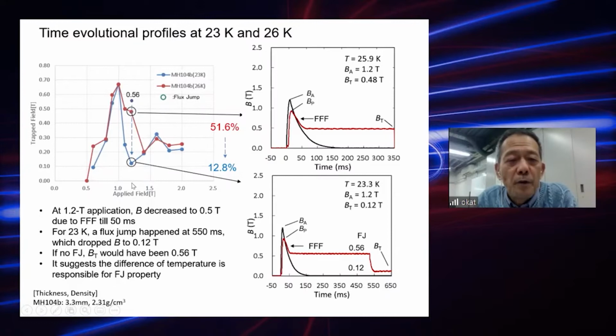So in the second one, these are for the areas of this 1.1 or 1.2 Tesla. At 1.2 Tesla application, trapped field decreased to 0.5, like 0.5 is here, due to the FFF till 50 milliseconds. This means that FFF, fast flux flow, appeared like this way until the 50 milliseconds, and then it goes straight like this to the BT.